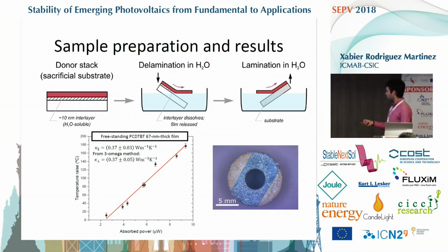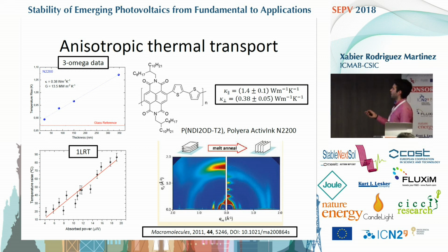And one of the most promising results we are getting now is that we are effectively looking at the anisotropy in the thermal transport by combining the Raman thermometry with the typical 3 omega method. We have been able to identify that in this polymer, the known N2200 polymer, which is typically used in the fabrication of thin film transistors, the thermal conductivity is fairly anisotropic depending on the direction, if it is in plane or out of plane.